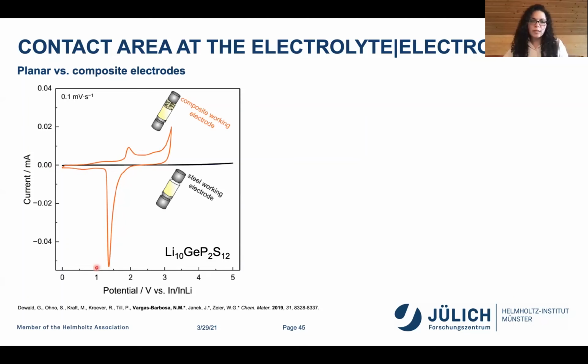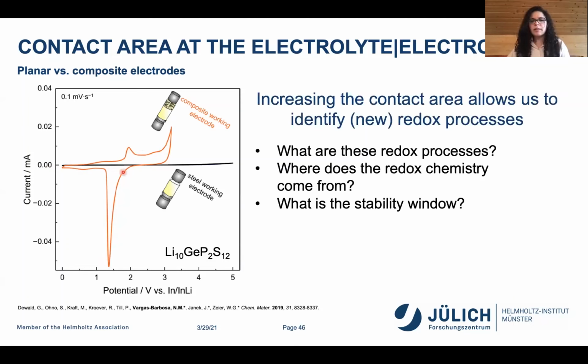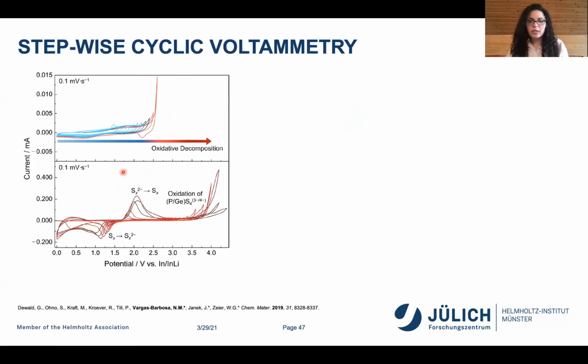But these redox peaks, where do they come from? And so now the question was, okay, they definitely degrade, and they degrade at potentials more negative than originally thought. But what is the actual stability window? How do we define it? And are these materials even good for anything at the end of the day? And so in order to get that kind of information, we did stepwise cyclic voltammetry.